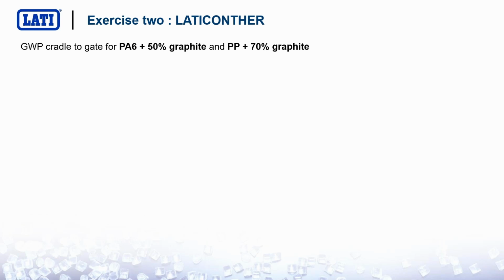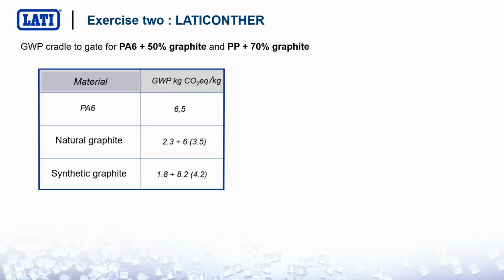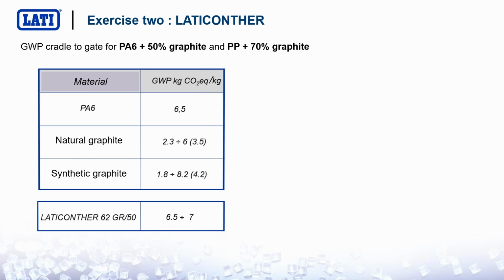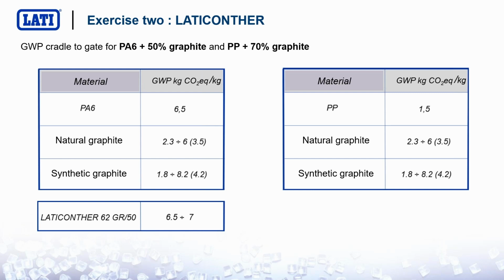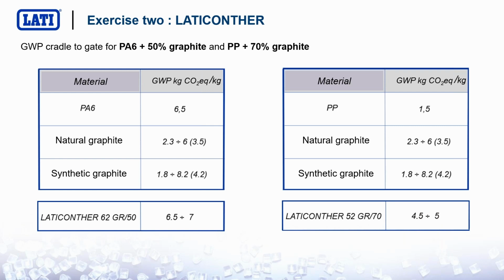So now exercise 2. Let's evaluate the global warming potential of thermally conductive plastics, because that's exactly what we are here to talk about. We have focused on two of the best-selling LATICONTHER compounds, nylon 6 with 50% graphite, and polypropylene with 70% graphite. For the nylon 6, you can see that the formula includes nylon 6 and 50% of natural or synthetic graphite, whose global warming potential is somewhat different, but it's more or less from 3.5 to 4. The global warming potential is 6.5 to 7 of CO2 equivalent per kilo. If we move to polypropylene, this number can be vastly reduced because polypropylene has a very low CO2 equivalent production when it is manufactured. So the global warming potential of a 70% graphite-based polypropylene thermally conductive compound is 4.5 to 5.